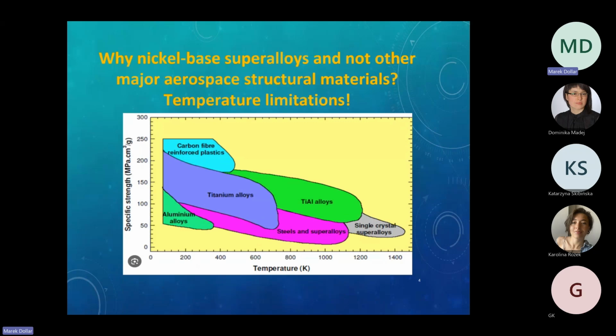When you look at this plot of specific strengths, so strengths divided by density, as a function of temperature, absolute temperature in this case, you can see here aluminum alloy. The melting temperature of aluminum is 660 degrees C, so practically they cannot be used above 400 Kelvin. Titanium alloys extend this temperature limit, but they're far away from what we need. As a rule of thumb, a number to remember, today we are talking about all these important properties at 1100 degrees C, so close to 1400 Kelvin.